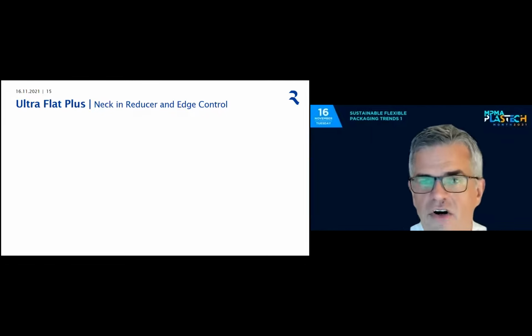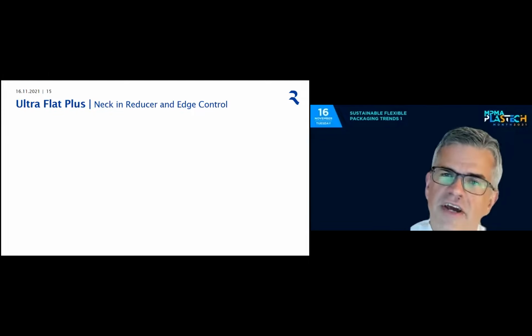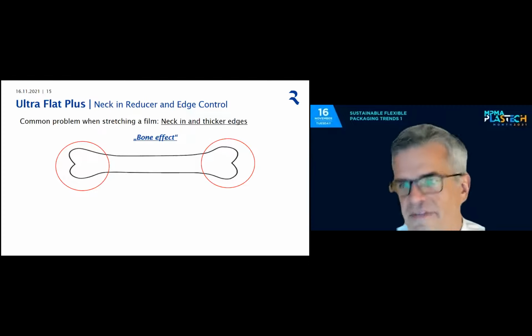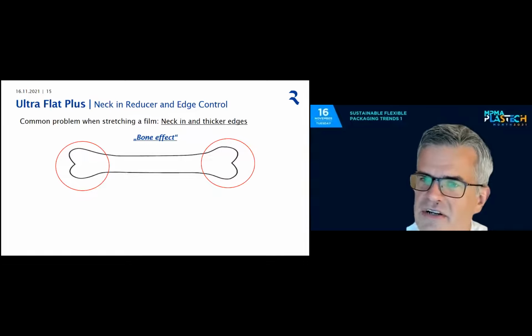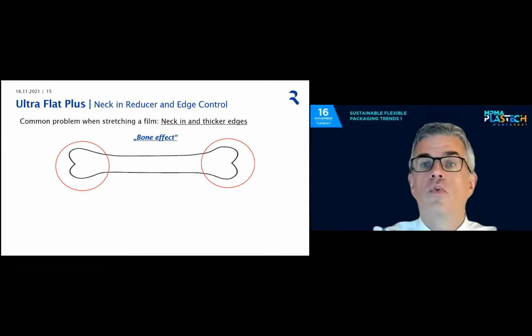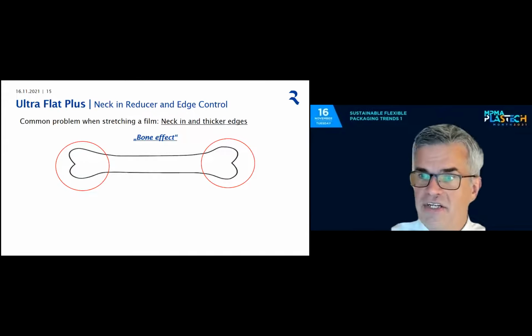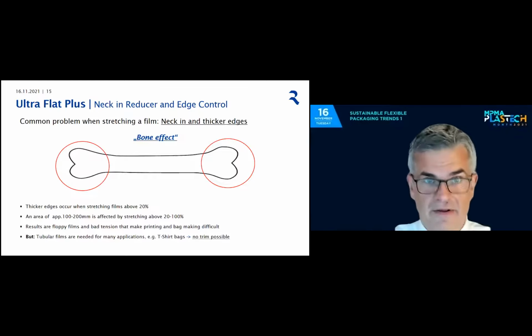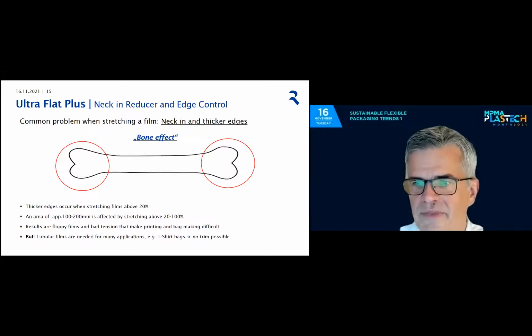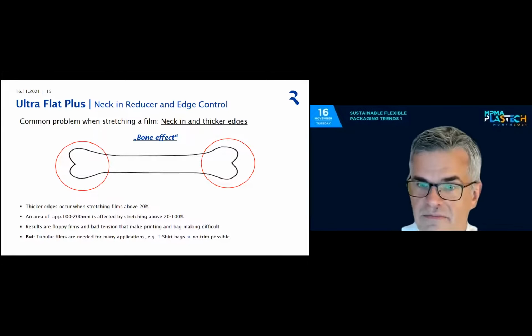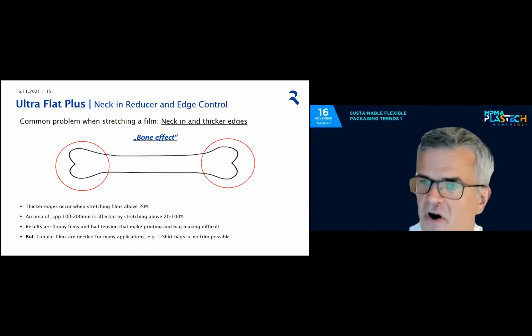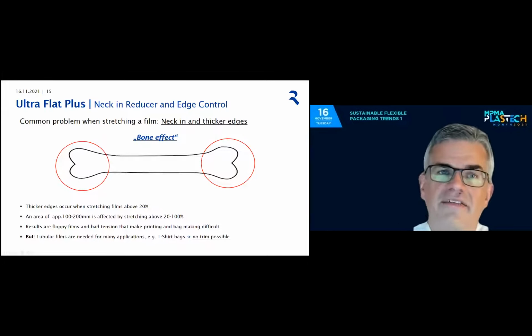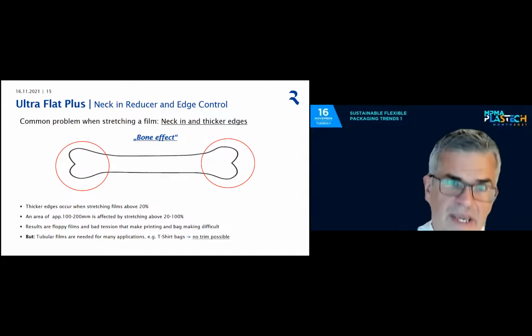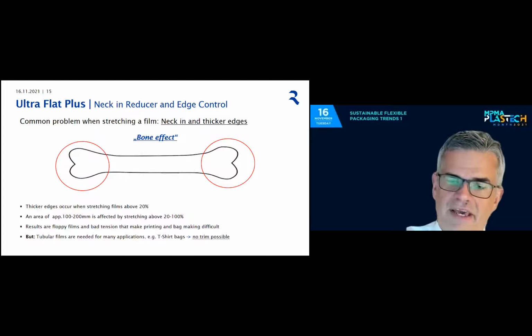And there's one thing which I have to tell you, which was mentioned already in the presentation of Francesco. If we stretch the film, I will get something called the bone effect. Unfortunately, stretching does not occur evenly across the whole width of the film. A common problem is necking and thicker edges. And if I make bags, I cannot cut away the edges. There's no way to do so. Unfortunately, it is above 20% thicker. So I have to take care of the left-hand side and the right-hand side of my tube. Again, trim is not possible because I have an application for bags.